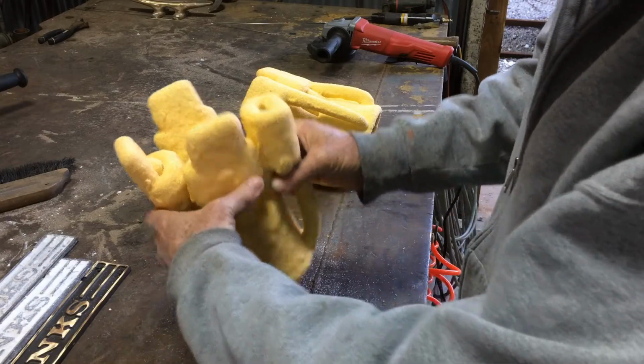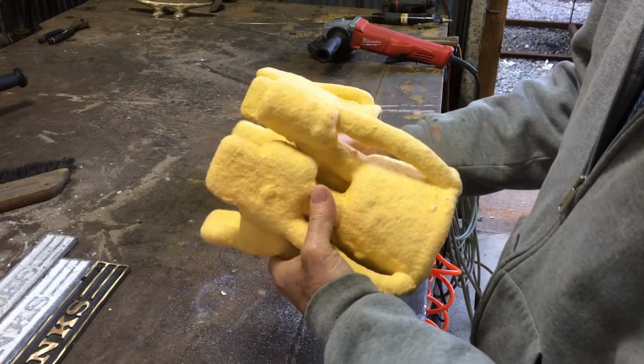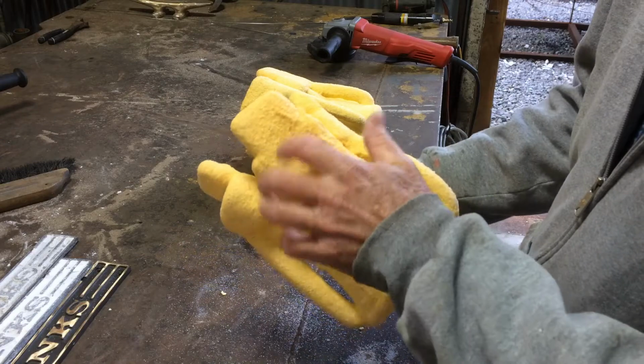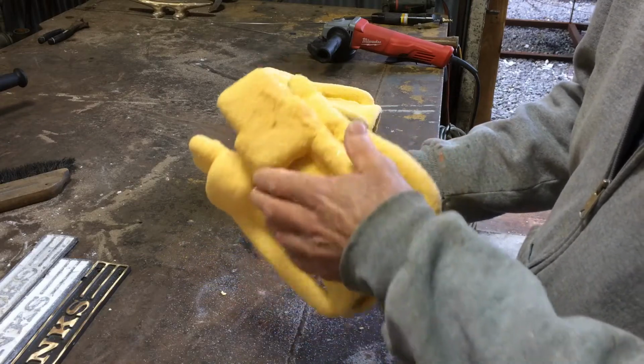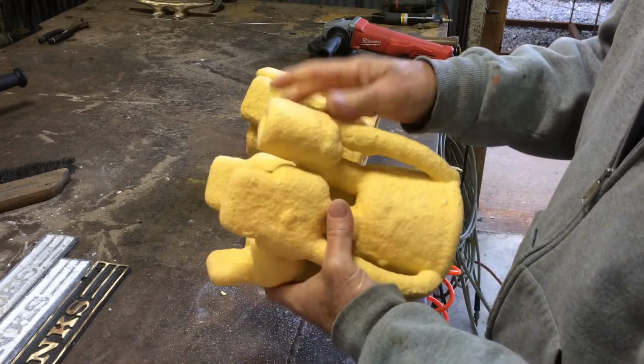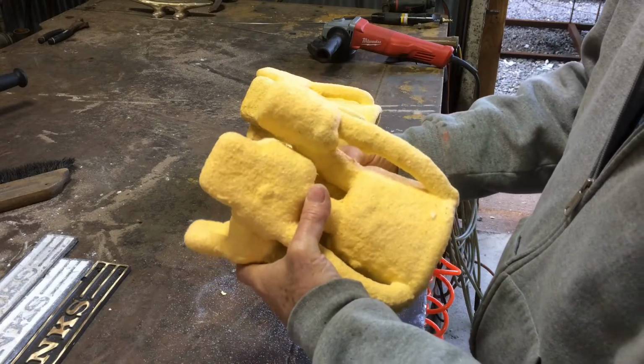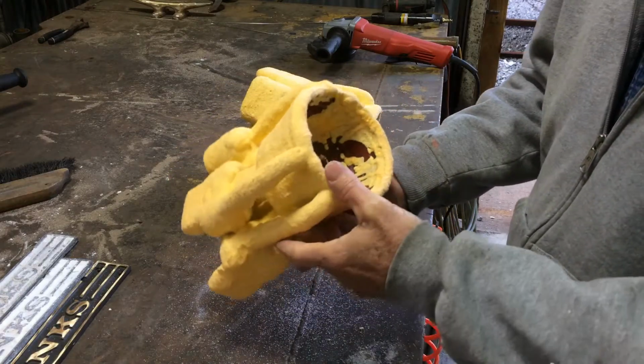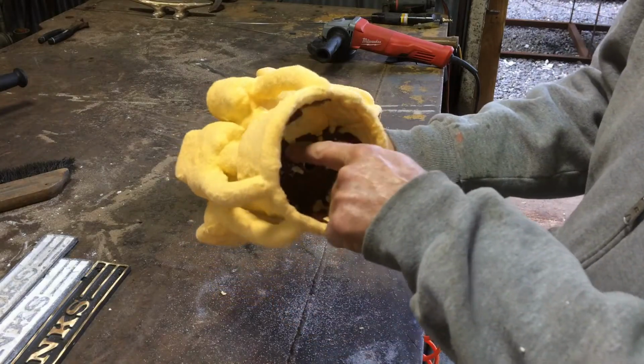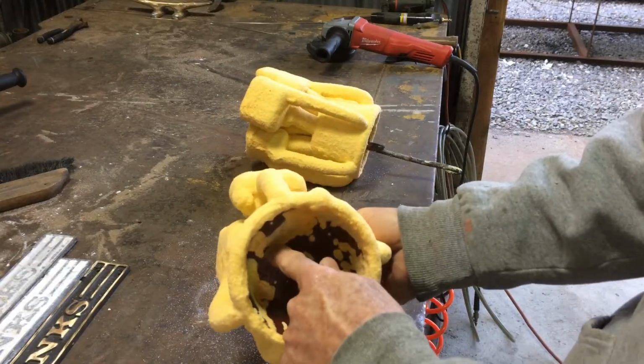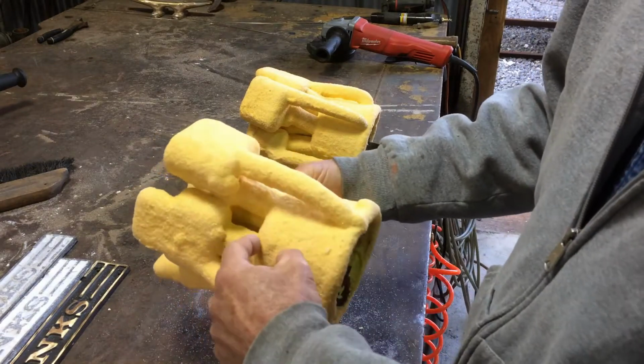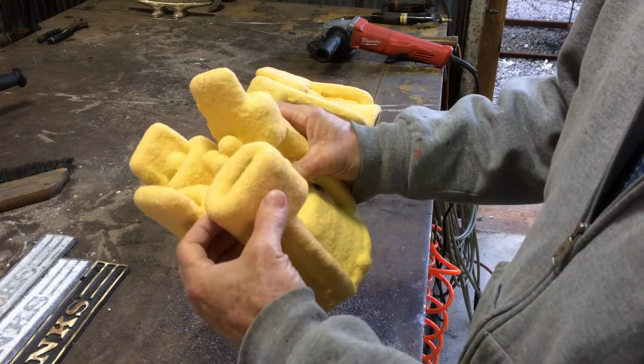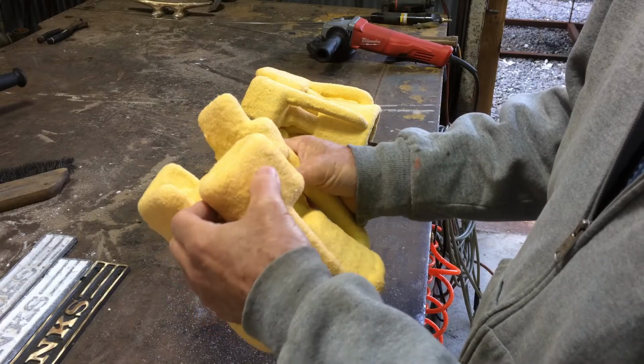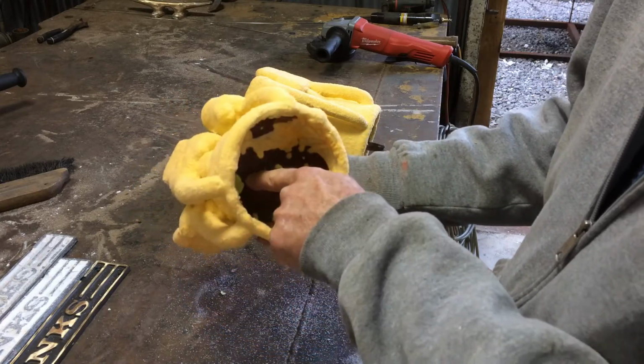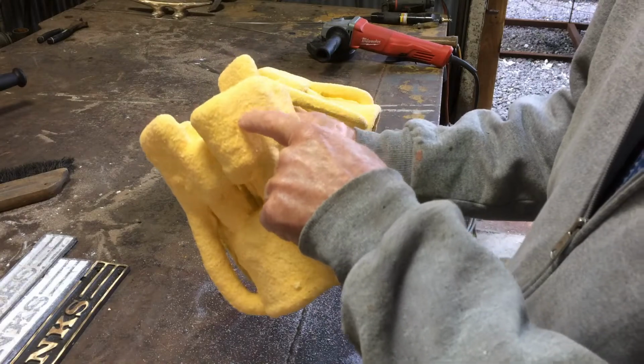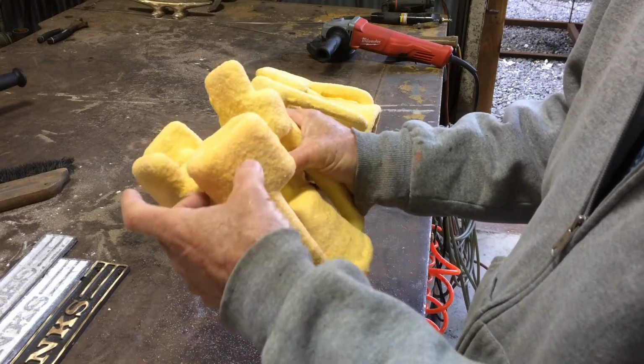But the problem with melting out wax is when you warm up wax, it expands, and the ceramic shell does not expand. So you have the potential of cracking the shell. Well, you have a pretty good chance of cracking the shell, especially because this wax that held the hook is about 1 inch thick, and all of this wax is more like 3/16 thick. So this wax is going to melt before this gets soft, and it's going to want to expand, and it'll have nowhere to go, so it'll crack the mold.